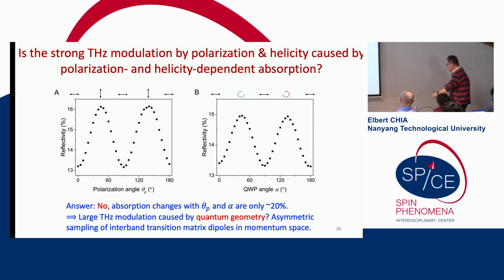So the next question is, could this large modulation with linear polarization and helicity be due to the fact that as you vary theta P or alpha, the absorption of the light by the sample has a large difference? And the answer is no, because when we measured the reflectivity of the sample as a function of the polarization angle and the quarter wave plate angle, we found that the change is only about 20%. So there is a suggestion that perhaps this large terahertz modulation is caused by quantum geometry. That is, at different points in the Brillouin zone, the transition matrix element is different, and so the sampling of these matrix elements is asymmetric in momentum space.